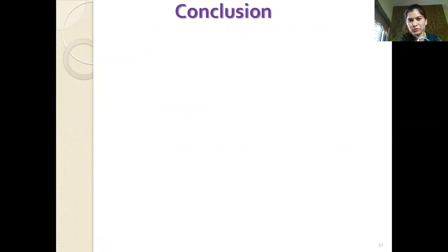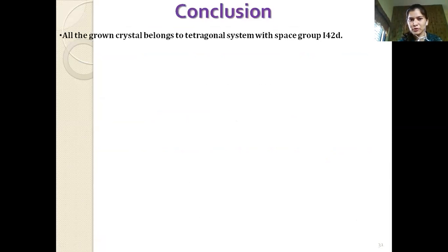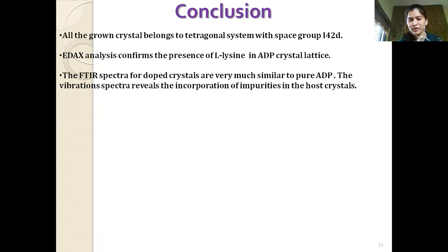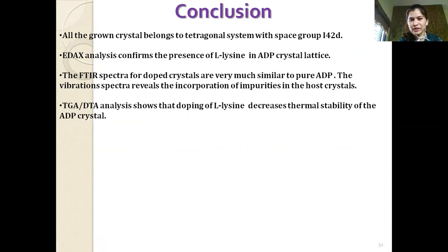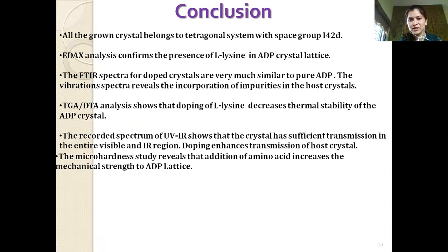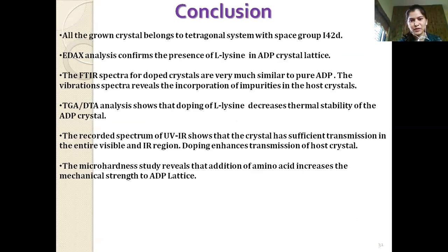Now concluding, all the crystals belong to the tetragonal system, and EDAX and FTIR confirm the presence of L-lysine, that is the impurity, in our ADP crystal. TGA-DTA thermal analysis shows a decrease of thermal stability of the ADP crystal due to doping, and UV visible spectra confirm sufficient transmission in the visible range, and doping enhances the transmission of our ADP crystal.